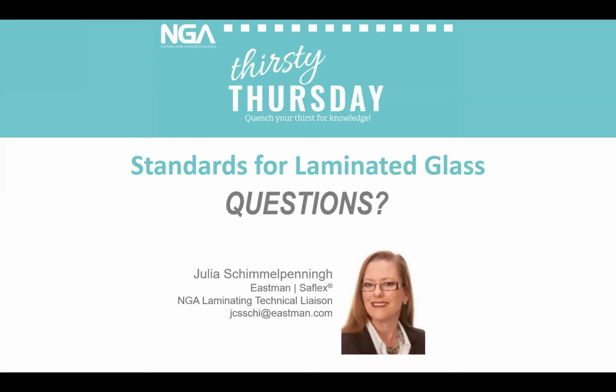And those factors can be anything from the moisture content being absorbed to stress levels at the edge, something like the bow and warp, or I call it the kissing edge. I know that that's not the proper term, but where you have edge kink that is separating. Sometimes if you have heat strengthened and tempered glass, you have stresses like that. Also, the use of clips or anything like that on the edge can certainly thin the edges of the laminate and then exacerbate the whole situation.